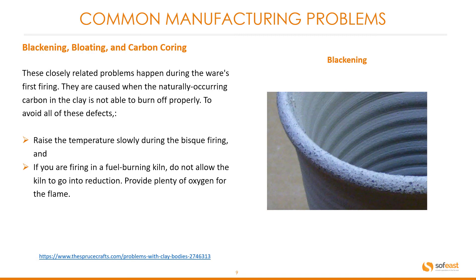Blackening, bloating and carbon coring. These closely related problems happen during the ware's first firing. They are caused when the naturally occurring carbon in the clay is not able to burn off properly. To avoid all of these defects, raise the temperature slowly during the bisque firing, and if you are firing in a fuel-burning kiln, do not allow the kiln to go into reduction. Provide plenty of oxygen for the flame.